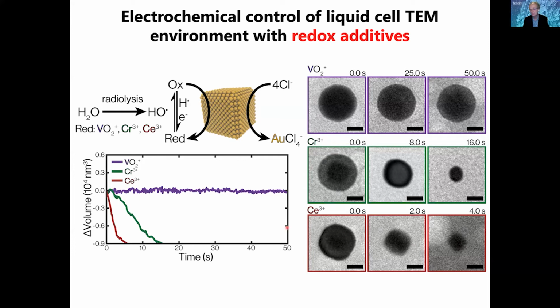Notice this is 4 seconds. In the presence of the chromium, the time scale here is 16 seconds. And you can see there's hardly any change in the presence of the vanadium oxide over a period of 50 seconds. So it's a much, much, much slower, unobservable on this time scale.